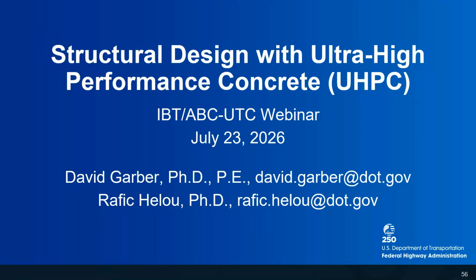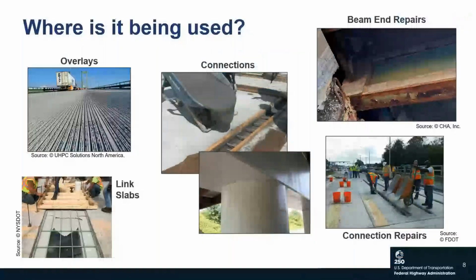Yes. Can this product be bonded to regular reinforced concrete piers with exposed reinforcing for a sustainable repair? Yeah, in slide 8, I think I show a picture of it. Just like overlays, you need to remove the bad concrete from your pier, then expose the coarse aggregate in the UHPC, and expose the coarse aggregate in the existing concrete, so you have good, exposed aggregate concrete, and saturated surface dry, and then you can place the UHPC, and usually you get a good bond for that connection.